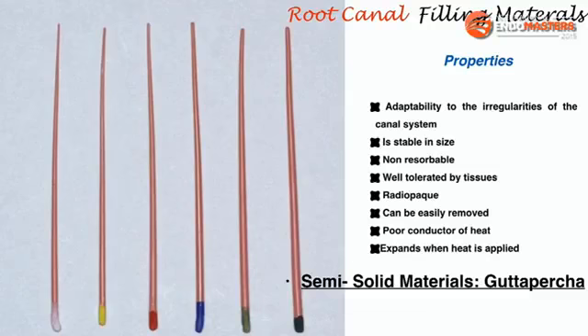Speaking about semi-solid materials, gutta percha has to come into the equation. It was introduced in 1847 by Hill, developing the first gutta percha root canal filling material, known as Hill's stopping. It is a poor conductor of the heat, so it gives us optimal control for the plasticity. At room temperature, gutta percha cannot be compressed or made to flow. Gutta percha can be made to flow if it's modified by either heat or solvents such as chloroform. This permits adaptation to the irregularities of the canal walls.